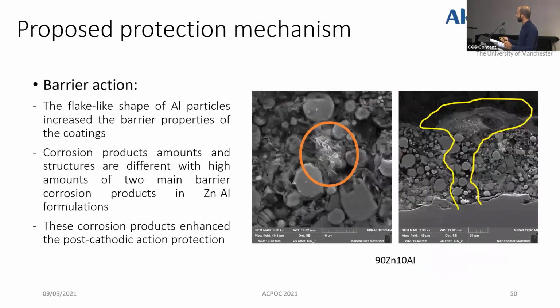As for barrier action, the flake-like aluminum itself offers some barrier action at the beginning, but the corrosion products' amounts and structure are different, with high amounts of two main crystalline corrosion products, simonkolleite and layered double hydroxide. So these corrosion products enhance the post-cathodic action protection.